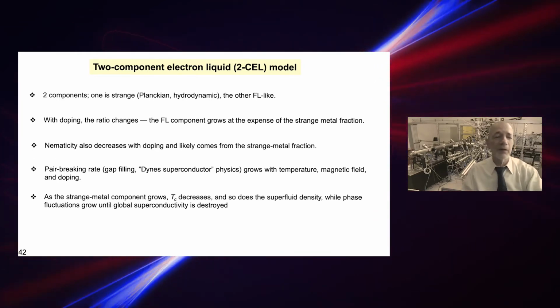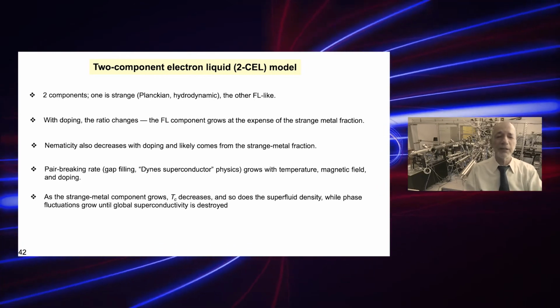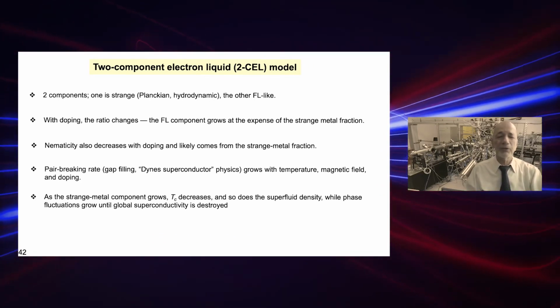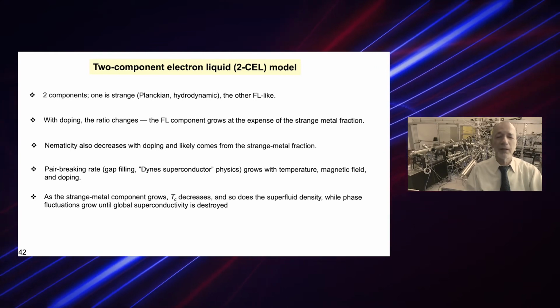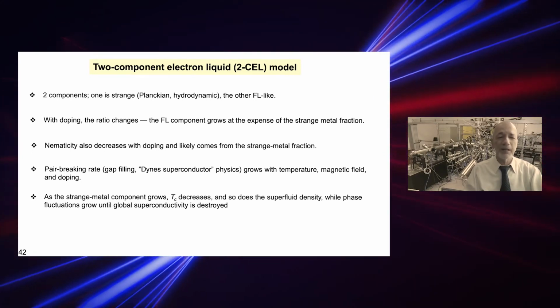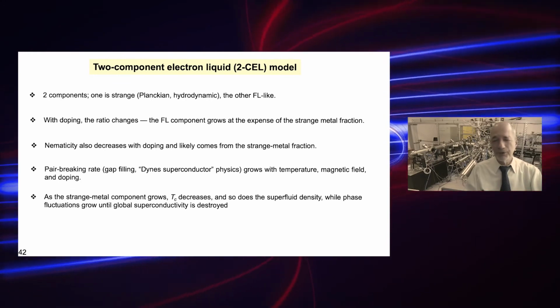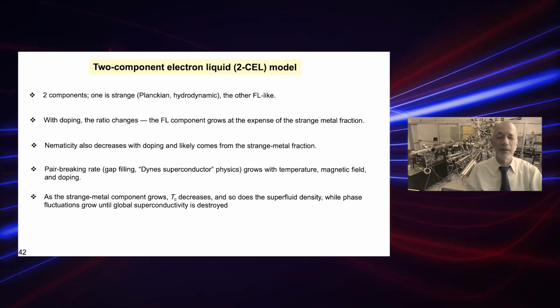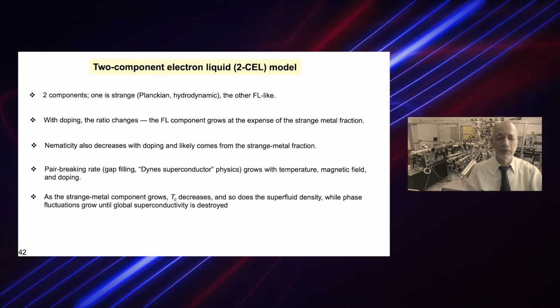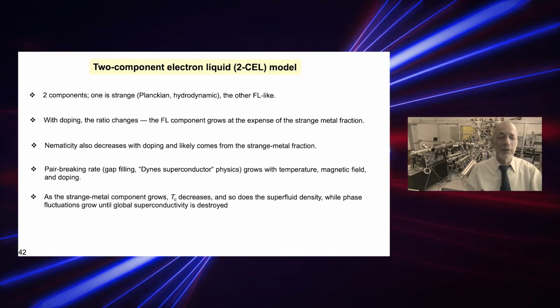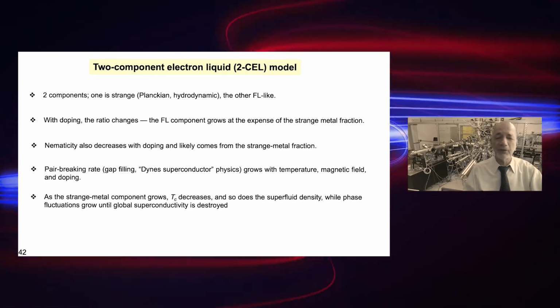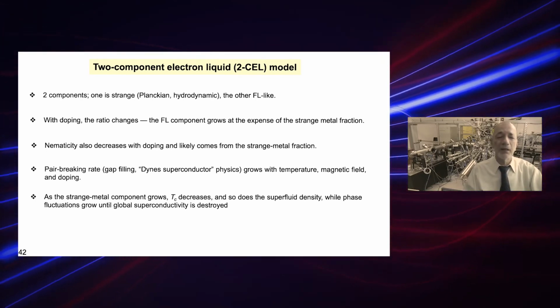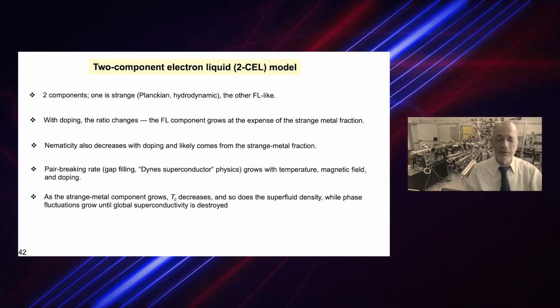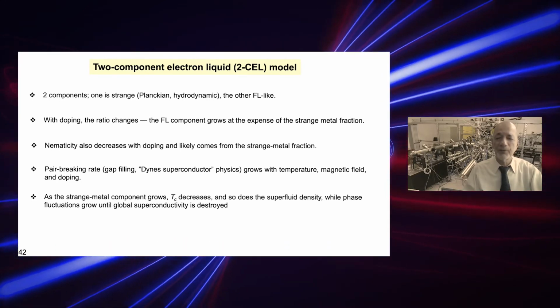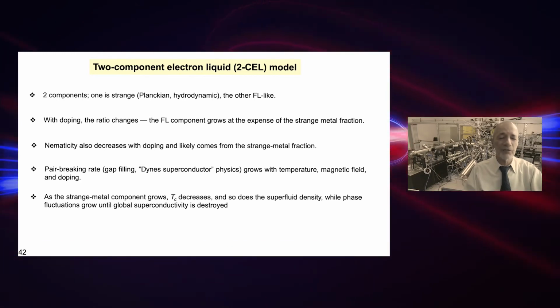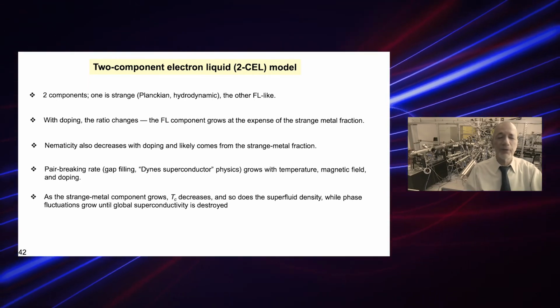And nematicity also decreases with doping, and it seems to track the strange metal fraction. We also see the pair breaking rate, which increases with temperature, magnetic field, and doping. And as the strange metal component grows, TC decreases, and so does the superfluid density, while phase fluctuations grow until global superconductivity is destroyed.